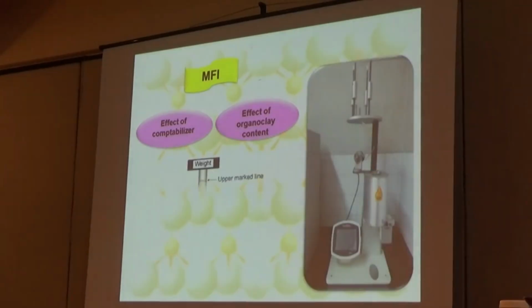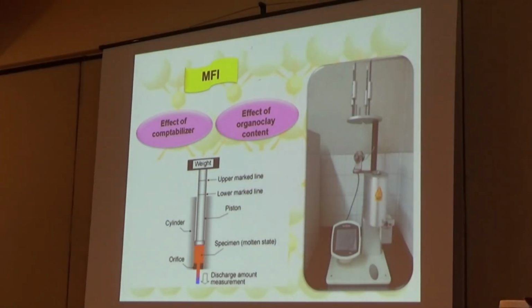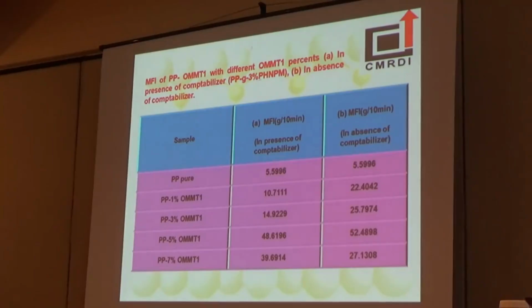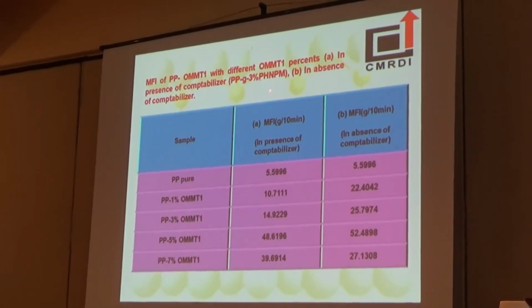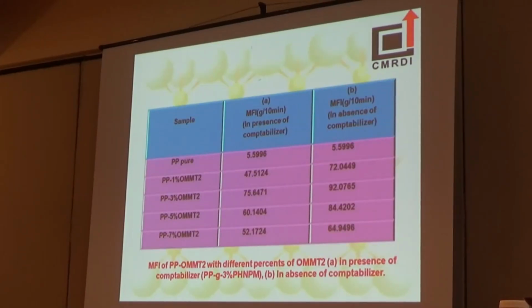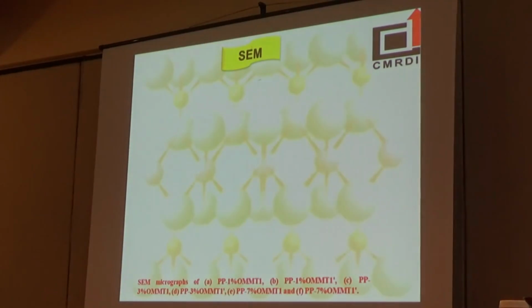Melt flow index measurements were carried out on all the samples, and two factors were studied. The first factor is the effect of the compatibilizer, and the second factor is the effect of organoclay percent. It was found that by increasing the amount of organically modified clay, the value of melt flow index increases both in presence and in absence of compatibilizer. The same trend is observed for the second two series.